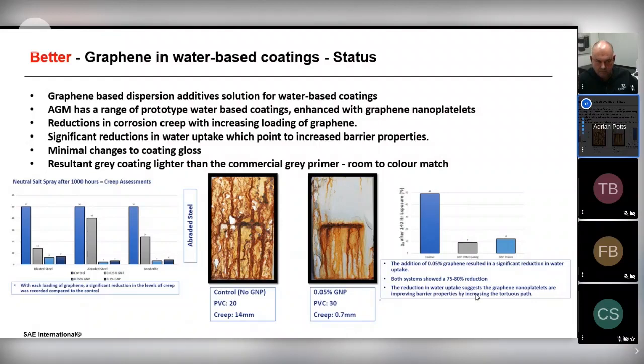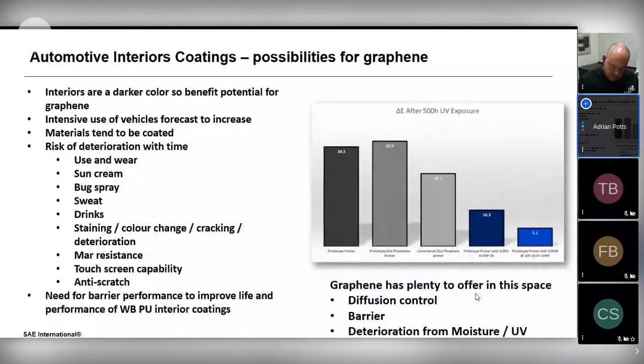Dramatic change to water transmission rate through a coating. And we're also able to manage color with very low graphene additions. So for things like direct-to-metal coatings, there's a great opportunity there. Lastly, really in this area, looking at automotive interiors, we see great potential utilizing the barrier performance of graphene in this area.